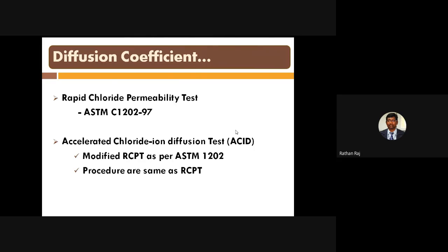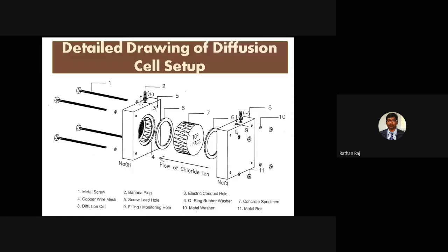This is the detailed drawing of a diffusion cell. The diffusion cell consists of two chambers or two containers. One container acts as the negative and the other acts as the positive. In the negative, sodium chloride (NaCl) solution is used, and in the positive, 3 normal NaOH solution is used. This is the concrete disc of 50 mm thickness and 100 mm diameter, which is carefully sealed with sealant to prevent the solution coming out from the chamber, and it will be screwed up. This is the schematic view of a diffusion cell.